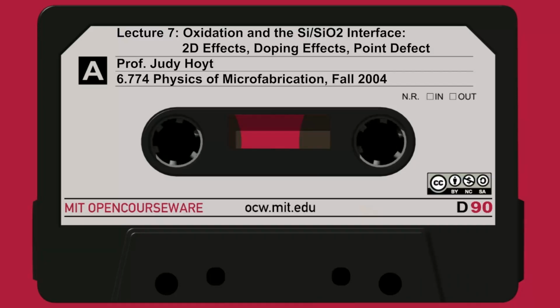And in fact, I just reminded you, you did some calculations on this in your homework. On slide 33, the vacancy concentration has been calculated for you as a function of doping concentration. Look where it takes off. Of course, somewhere right around 10 to the 19th, it really starts to take off. That's exactly where Ho found that the B over A coefficient took off, right where the vacancy concentration is going up as a function of doping.